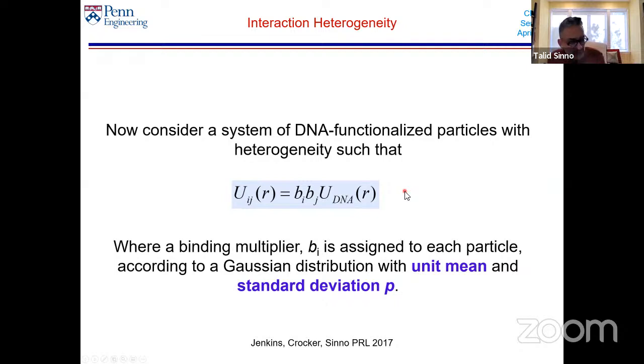So imagine now that I have a bunch of particles and there's a Gaussian distribution of binding strengths between the particles. And this distribution might have a mean of 1 and a sigma of 0.1. Okay, so that's a typical amount. And this sigma, this standard deviation, or I call it P here, depends on the chemistry. But for a lot of the chemistries that people use, it's typically in the area of 0.1.